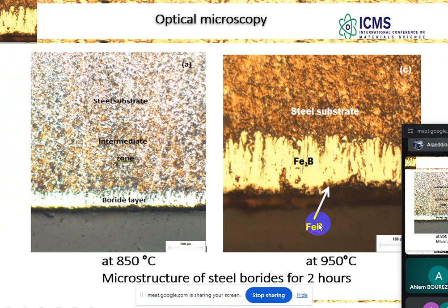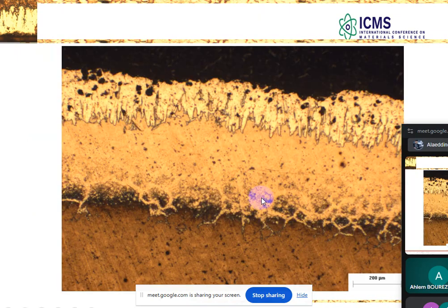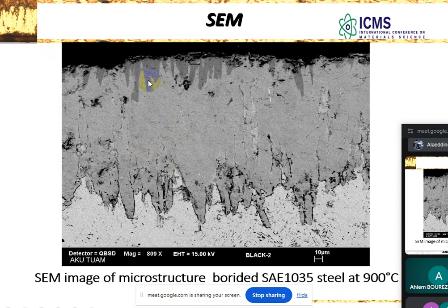We compare our results with previous results that we have published before. We used steel, carbon steel, and stainless steel for boride layers. This is the intermediate. This is the steel. This is the transition zone, and this is the boride layers that we have. And down here is the substrate. So this is iron boride, FeB, and this is Fe2B, and this is the substrate.